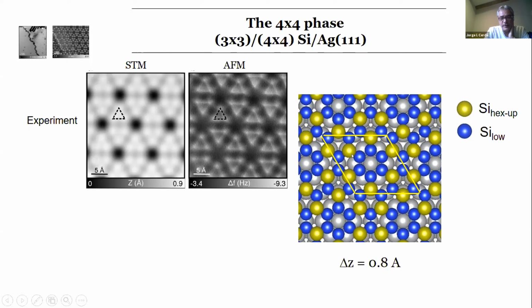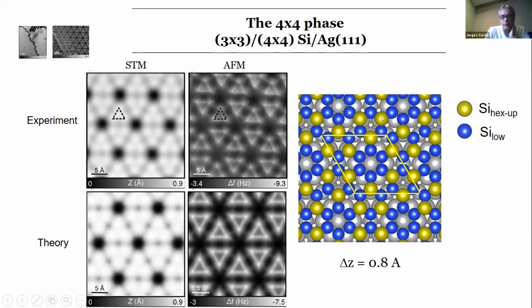It's kind of a silicene network where we have two types of atoms, ones which are sitting a bit higher than the other ones. Okay, the corrugation between the two is about 0.8. If you do the simulations for this structure, this relaxed structure, we see that we get a very nice agreement with the experiment. The triangles that we are seeing in the experiments are simply these high-lying silicon atoms.